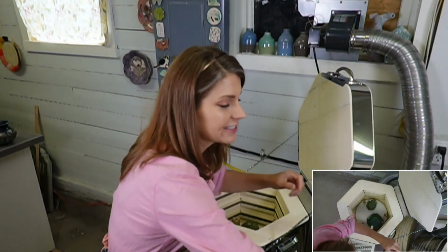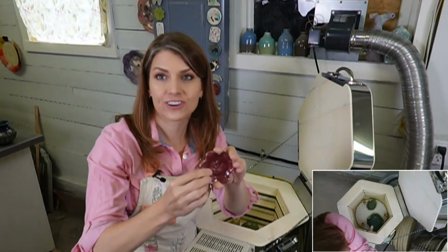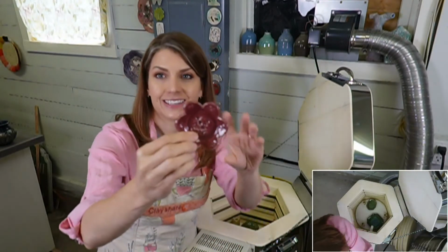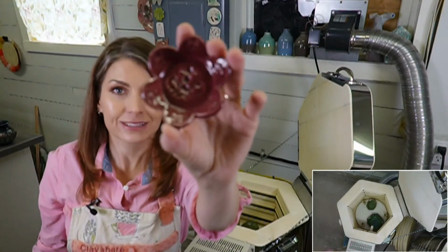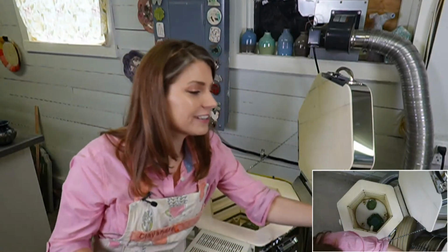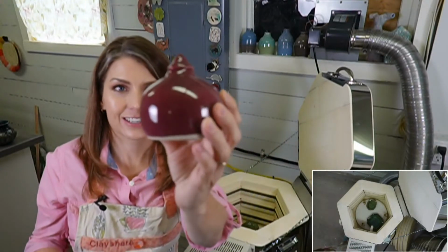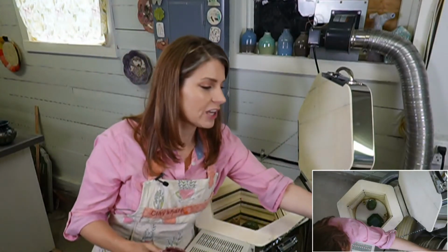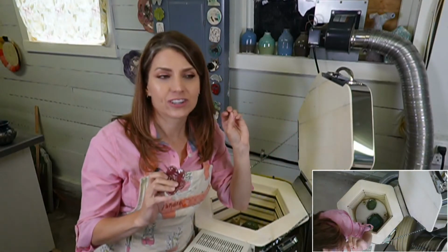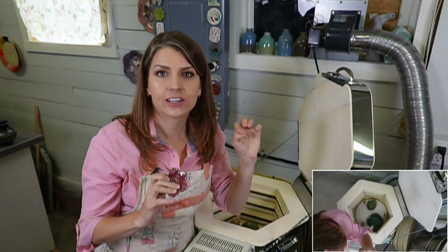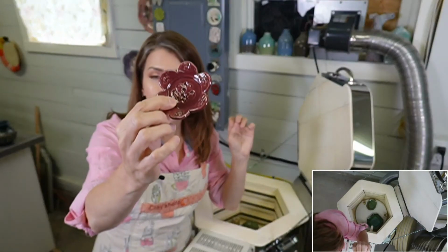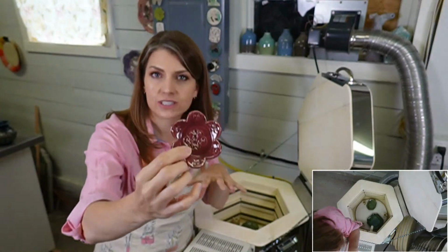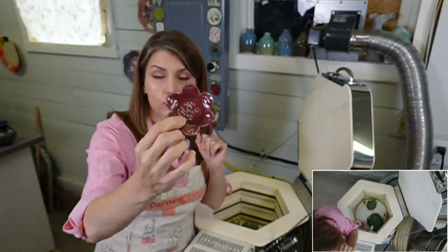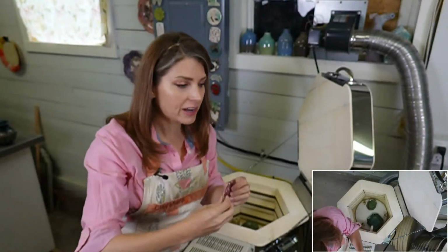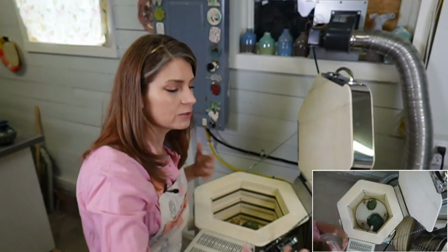So the cranberry, I see someone mentioned it looks like a reduction red. It does. It looks like a copper red, but without so much of the fuss, right? So you could definitely fire that in oxidation. This will not look like this in reduction. No, not at all. Nothing like that. It would be green in reduction. It would be a dark olive green in reduction, this glaze here. And it's formulated for cone 5, cone 6. This likes cone 6 really well. And as you could see, it did great at cone 5. So if you go to 6, you might be able to push it to 7.